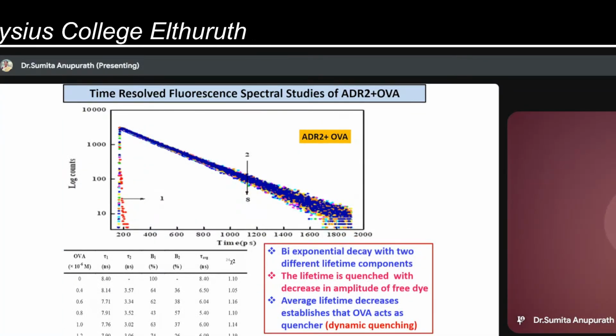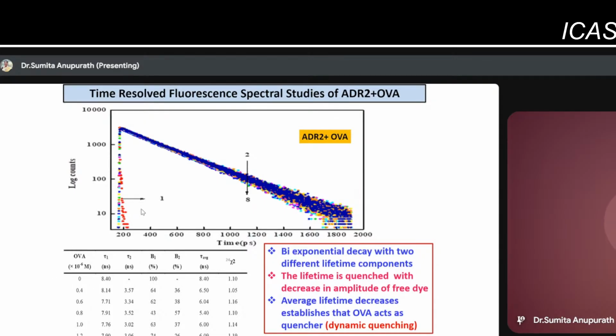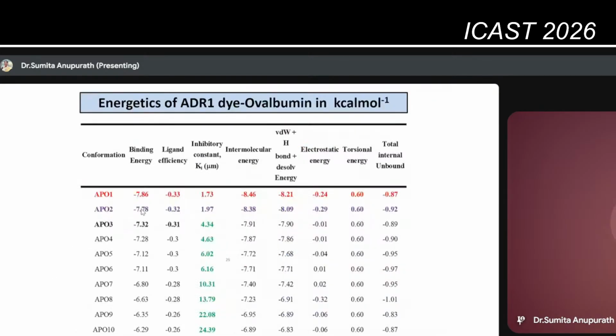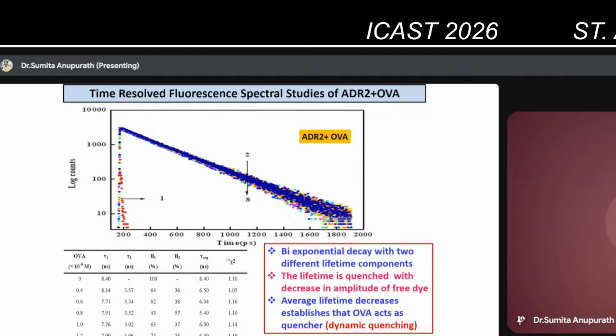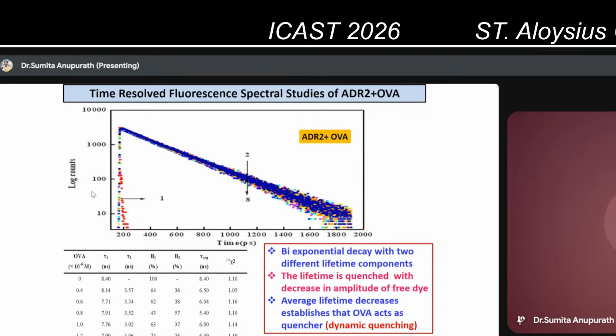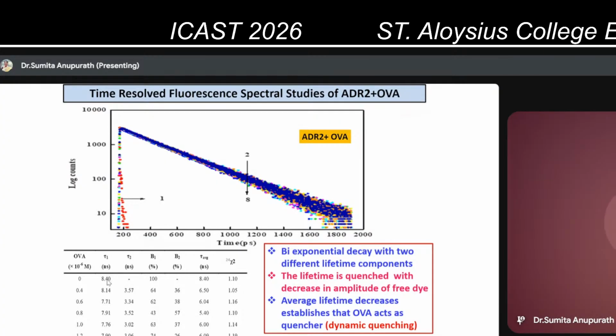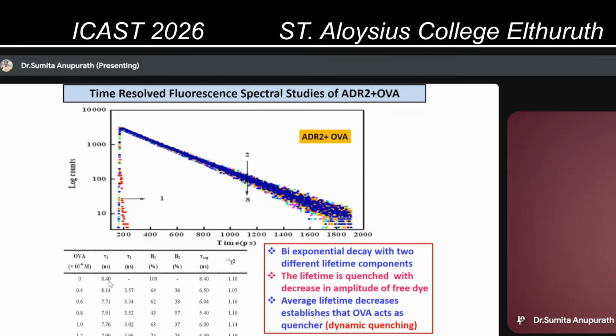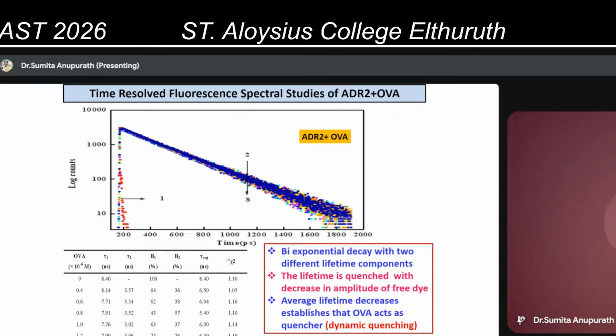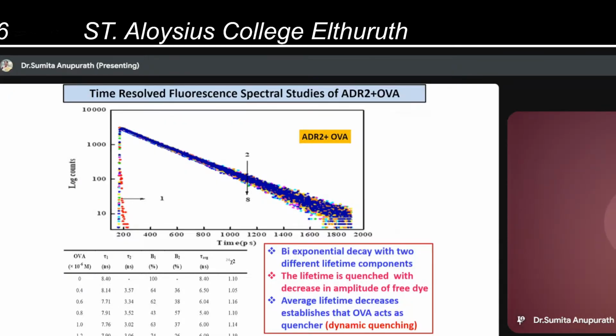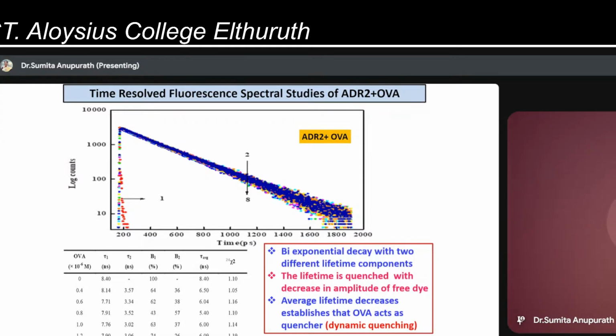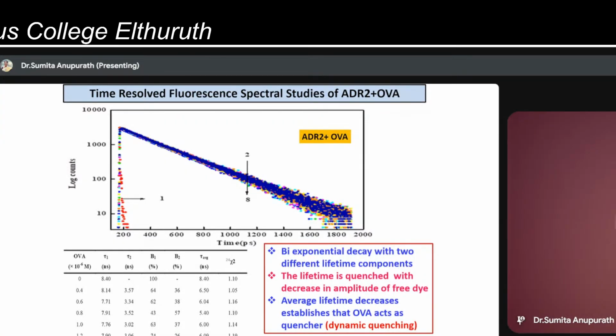Now let us see what was the case when we introduced the protein to the non-PET dye. Here, the single exponential decay changed to bi-exponential decay with two different lifetime components. So here, the values show that the lifetime is quenched. You can see from 840 picoseconds, it reduced to 790 picoseconds. So here the lifetime is reduced, or you can say ovalbumin acts as a quencher here. It behaves as a quencher, and so that was totally different from what we observed in the PET dye.